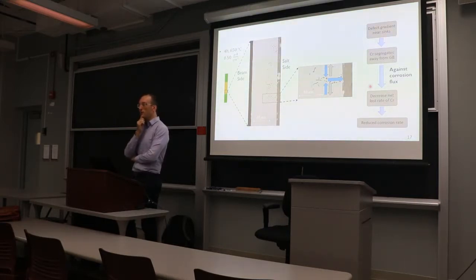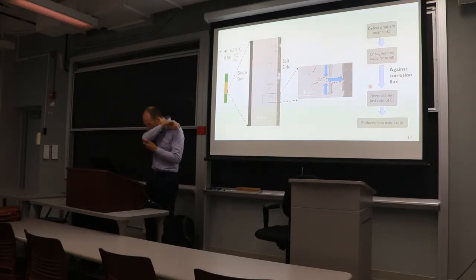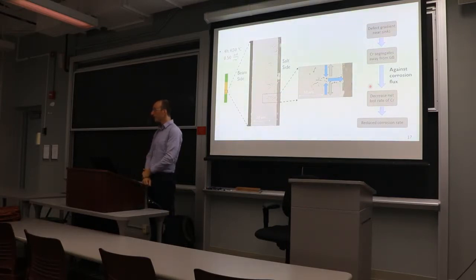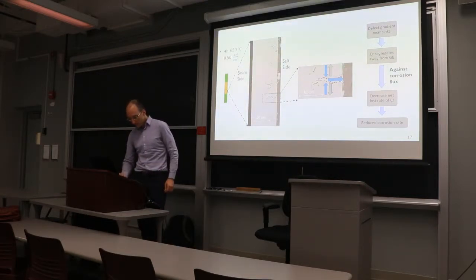So, do you guys have any questions on this? For me to do a little more explaining. Yeah? Can you exclude a temperature effect? When you increase the current, you are also increasing the temperature by almost a factor of 2, right? Because you're pumping more current in, which means the sample heats up more. I don't know where a thermocouple sits, but one challenge is always, can you verify what your temperature is at the backside of your sample, on the salt contact?